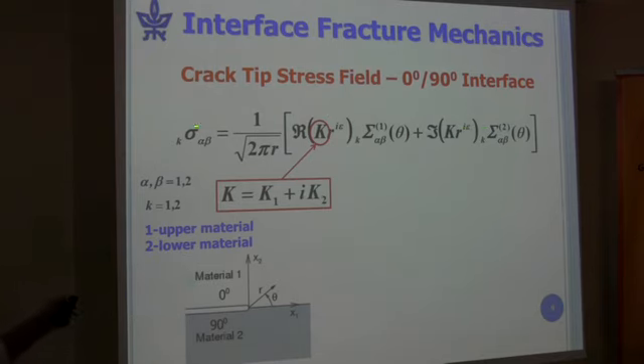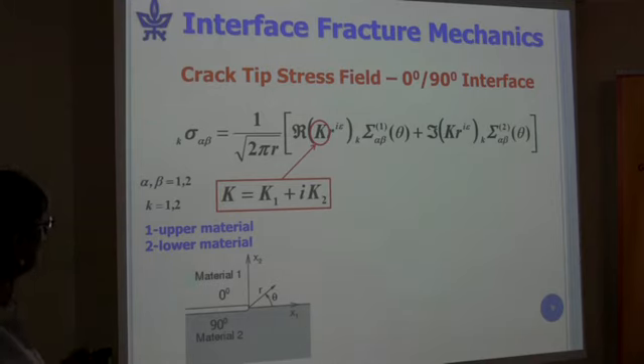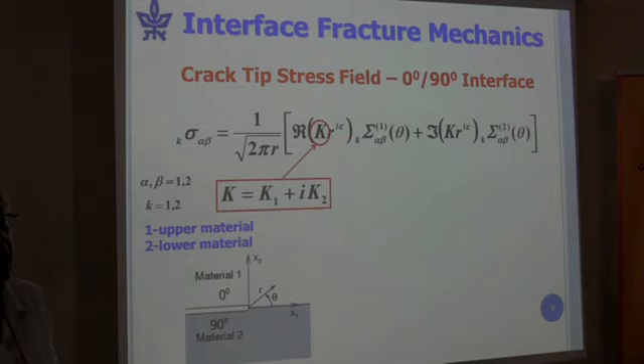And so if we look at the units, this is force over length squared, and so we have a length to the 1/2. So this entire thing is force times length to the -3/2, but then K has a length to the -i epsilon, which makes crazy units. And if you change the units from millimeters to meters or vice versa, you don't have a relation between K1 and K2 as you would have in the ordinary homogeneous isotropic material. But not to worry, because you can keep track of it. It's just mathematics, and one can get a handle on it.